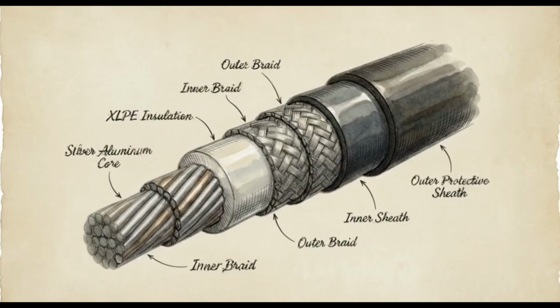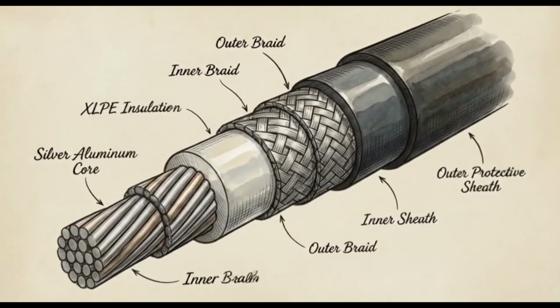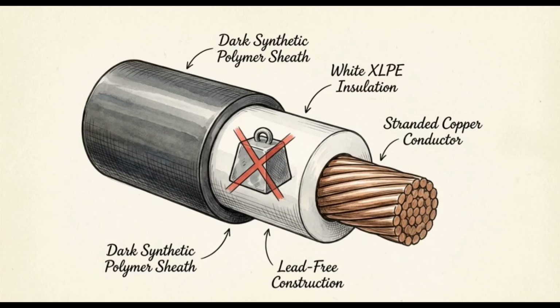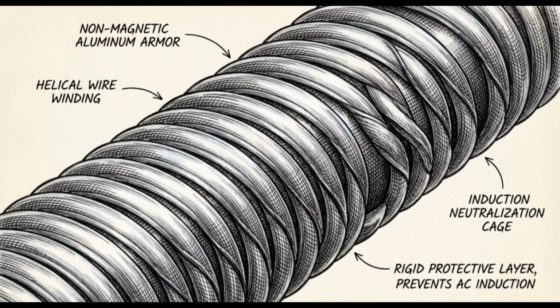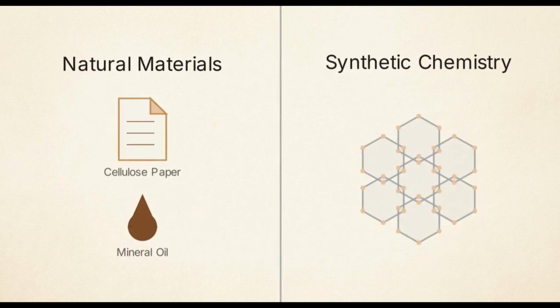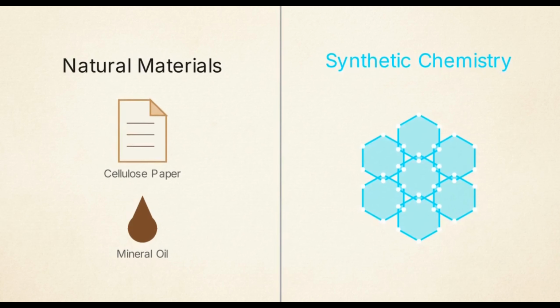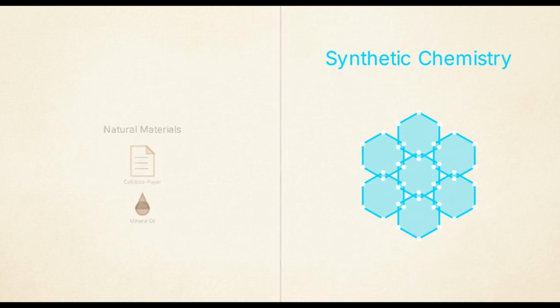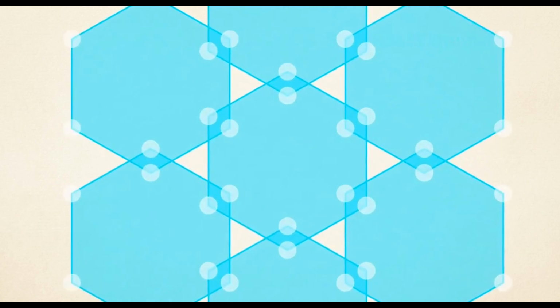We now have a fully assembled modern distribution cable. Its aluminum core, chosen for economic conductivity, is locked firmly inside a high-heat XLPE thermoset. It is sealed within synthetic polymer sheaths to shed the crippling weight of historical lead, and finally wrapped in a protective cage of non-magnetic wire to neutralize AC induction. Advancements in synthetic chemistry allowed manufacturers to permanently phase out heavy, failure-prone natural materials like paper and mineral oil.